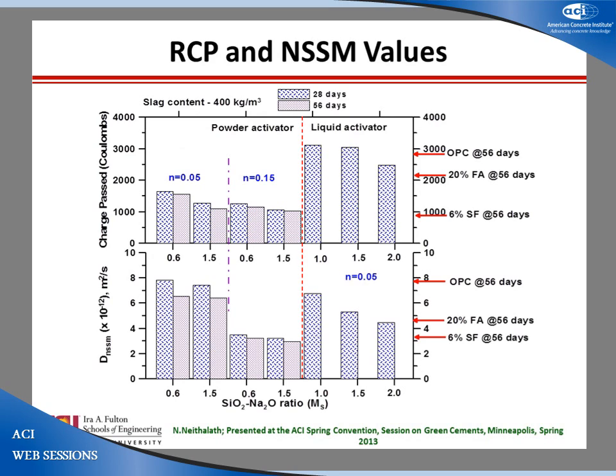You can certainly see that the powder activators have, remember, lower strengths but much lower transport values with respect to RCPT values. When you look at non-steady state migration, it's not very different between solid and liquid except when your alkalinity is very low. So this itself will tell you straight away that there are microstructural differences between these two activated materials, and it also tells you RCP is not a great way to characterize mixes where you have these kinds of changes.